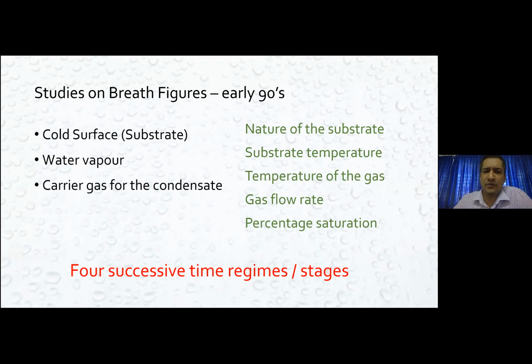The first stage is nucleation, which usually follows the exponential time kinetics of a to the power 1/3. The parameter A is a function of substrate temperature, the relative humidity, the flow rate, and so on. Generally, all the people observed that it is a 1/3 exponential function. Then there is the growth of the droplet. Once the nucleation is done, there is a growth of droplets, which generally goes by 2/3 of the exponential function.